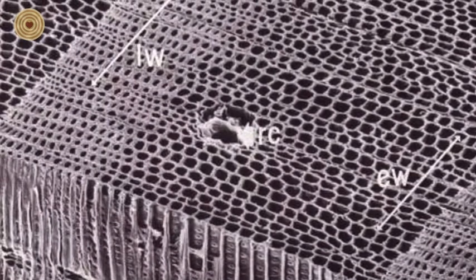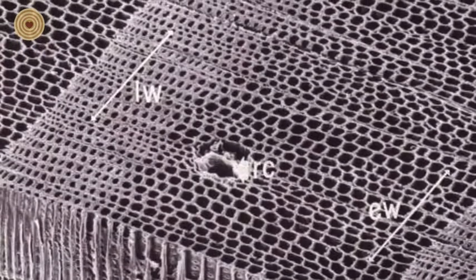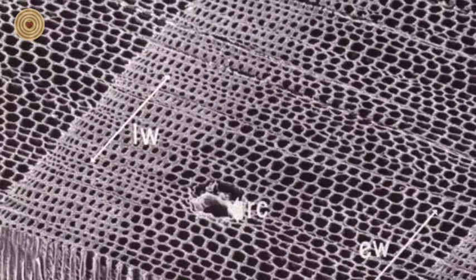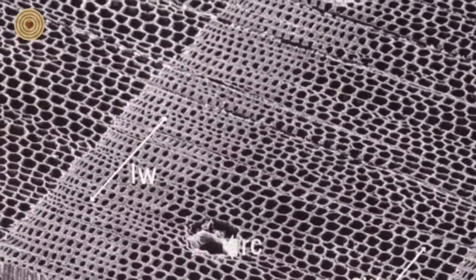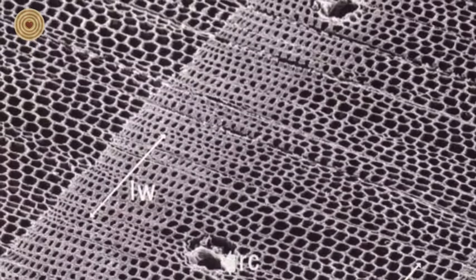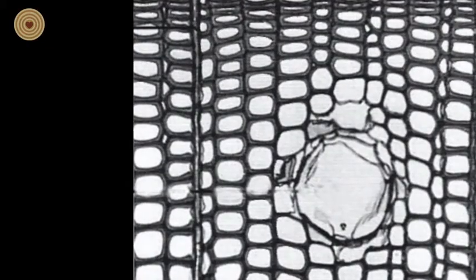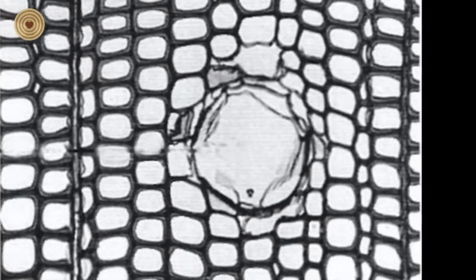Going back to our wood block, one other feature of importance to note on the cross-sectional surface is the presence of resin canals, which are composed of specialized parenchyma cells that are arranged to form a small tube. And yes, these cells produce resin or pitch, which we find exuding from the cut surfaces of many softwood trees. The resin canal can be a useful diagnostic feature, with some softwood species having very few or no resin canals and other species having relatively large and abundant resin canals. Further, some tree species will produce resin canals only when injured.